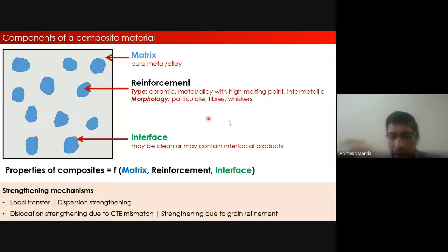And the third important thing, which should be given a lot of emphasis, and which at least materials engineers deal with in quite some detail, is the interface, which is very often ignored. But it should not be ignored. The interface plays a very, very crucial role. So what is the interface? The interface between the reinforcement and the matrix. As far as possible, it should be as clean as possible. That means if you look into this interface using a scanning electron microscope, you should be able to see that you do not form any interfacial products in this interface region, because if the interfacial product is weak, it can deteriorate the overall mechanical properties, or for that matter any properties of your composite.